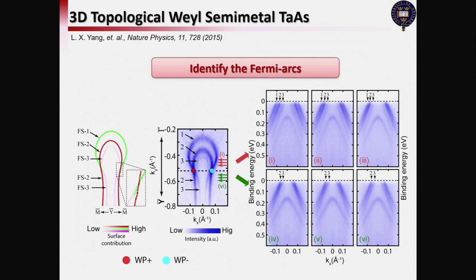Then we were able to see the surface state Fermi surface, and you can see there are three pieces of Fermi surface up here and two pieces down here, and the one piece, the green one, is the surface Fermi arc that terminates at these two points. So then we proved that there are Weyl points. So this material, tantalum arsenide, is a topological Weyl semimetal.